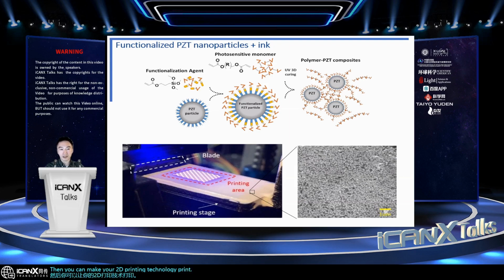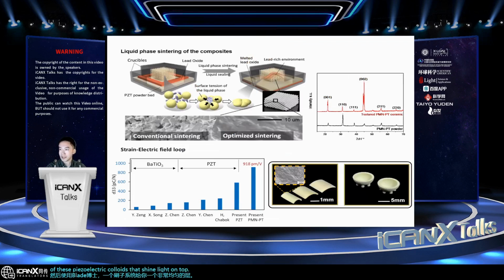So this makes this material really viscous. So it gave us a lot of challenge to use a stereolithography-based system to print them. So we have to come up with a hybrid approach, which is you have to use a nozzle to squeeze this piezoelectric paste. So it's basically like toothpaste. You have to squeeze this paste and then use a doctor blade, a brush system, to give you a really uniform layer of this piezoelectric colloid, then shine light on top and then do your layer by layer fabrication.